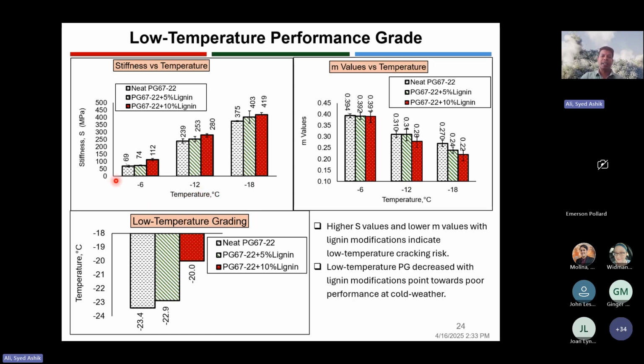And we found that with the addition of lignin, the stiffness increases significantly. And with temperature, obviously, as we go to lower temperature, we have seen a significant increase in the stiffness value. For the M value, with the addition of lignin, we have seen a decrease in the M value. So what does it mean? We are seeing that at low temperature, the stiffness will go high if we have a higher amount of lignin, but the stress relaxation will suffer if we add a higher amount of lignin, right? And that could be a problem for low temperature cracking. So low temperature cracking resistance wise, that could be an issue with the addition of a high amount of lignin. So we have to keep that in mind.